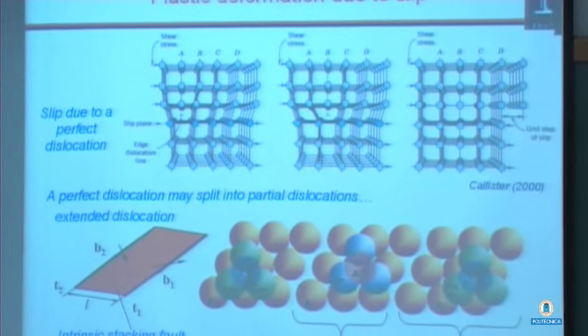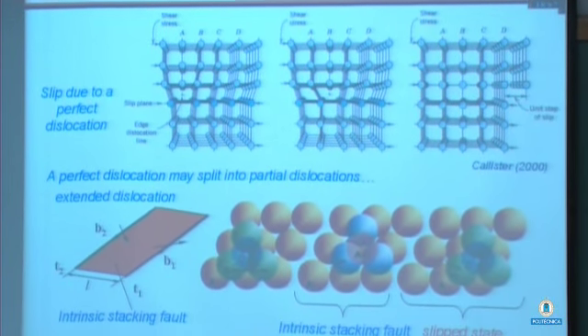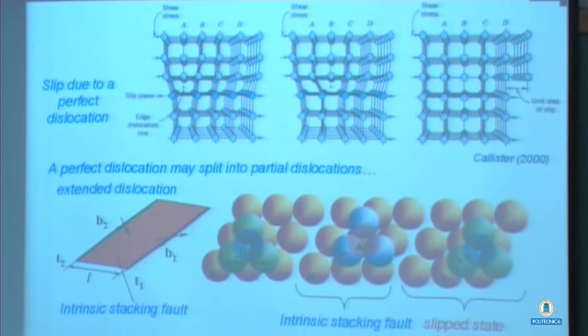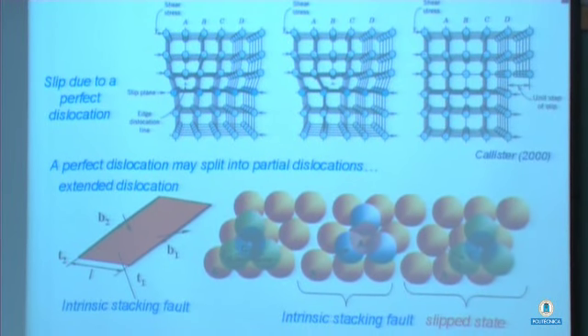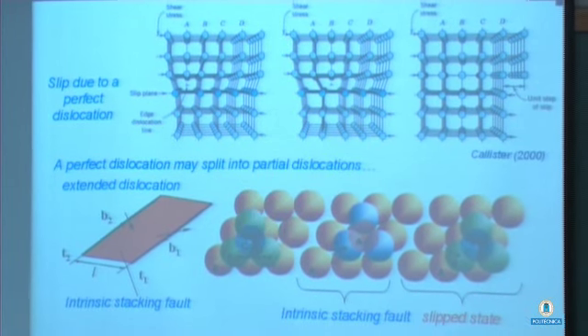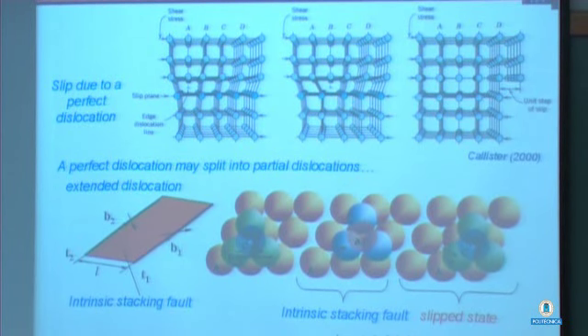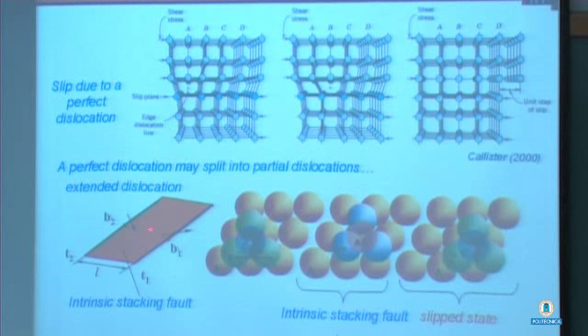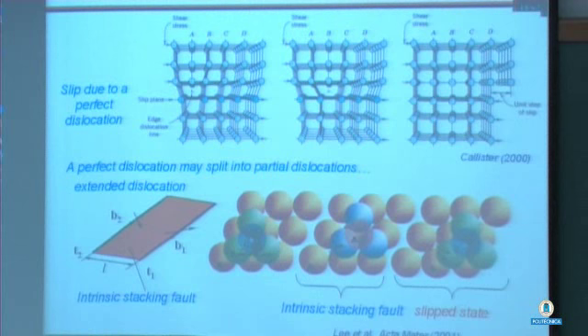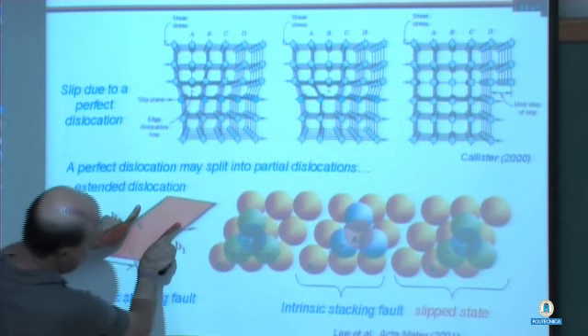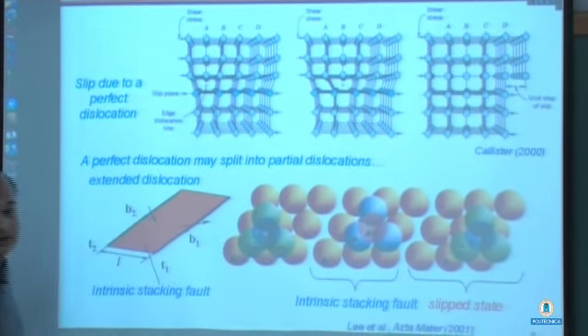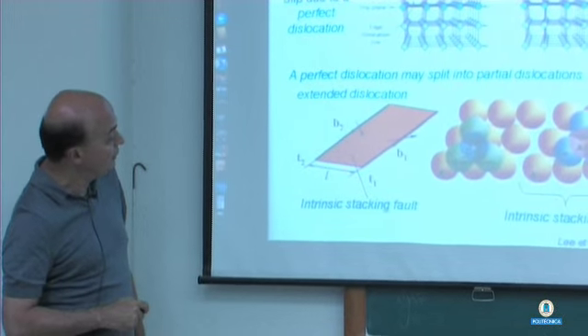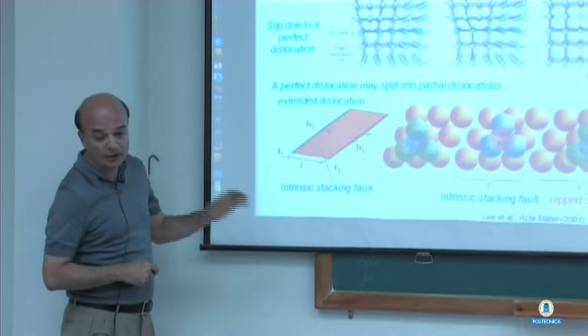Now, in FCC materials, FCC metals, the motion of the dislocations are via the motion of partials, okay, not perfect dislocations, but these are the partials here. B1, B2 are the partials. And then there is this intrinsic stacking fault in between. So the motion of the dislocations would be the motion of this entire fault. And the width here is, I'll come to that.